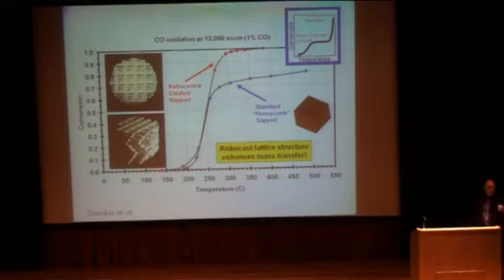So imagine if you have water going through a hose. If you put that velocity up really high, the water in the center of the hose is never going to actually get to the wall. So you'll never be able to complete the reaction. And that's what we did here. We put the flow rate up high enough so that the reaction actually couldn't occur totally within the honeycomb because it was going through a straight-through channel. But with the exact same conditions and the exact same amount of catalyst in a Robocast structure, we can get that reaction to go all the way to completion.